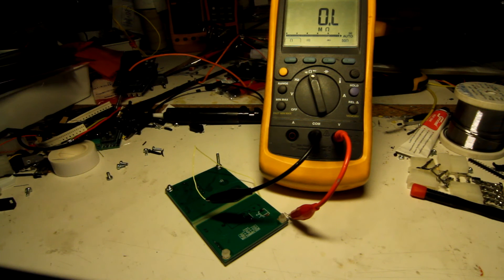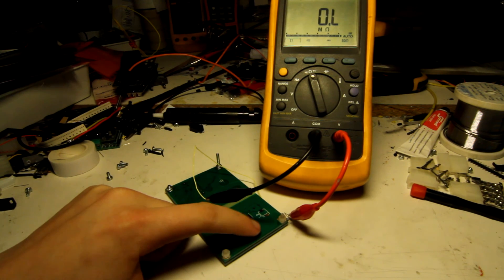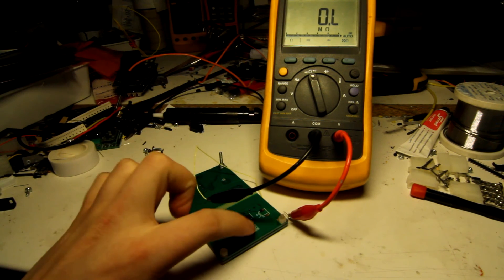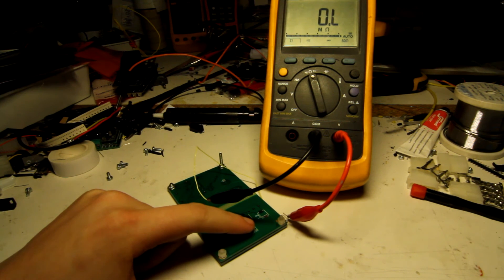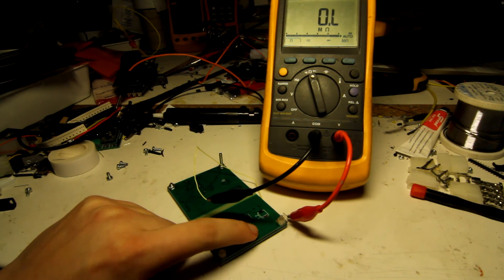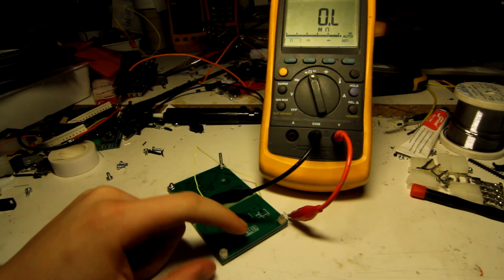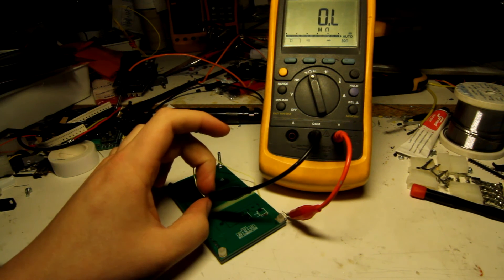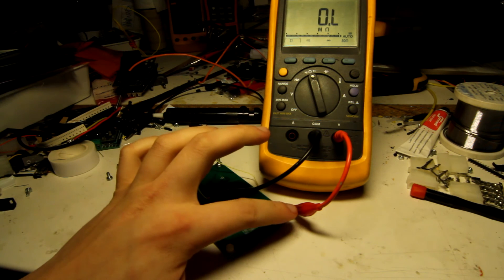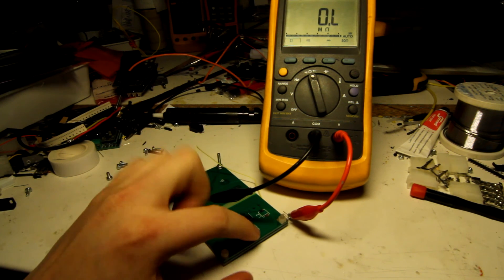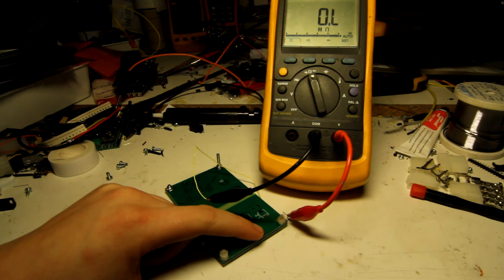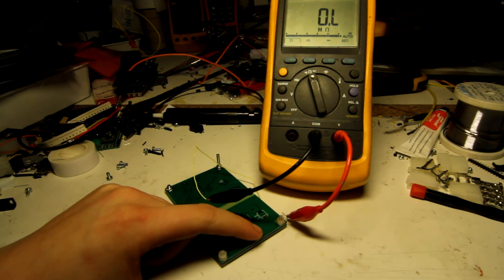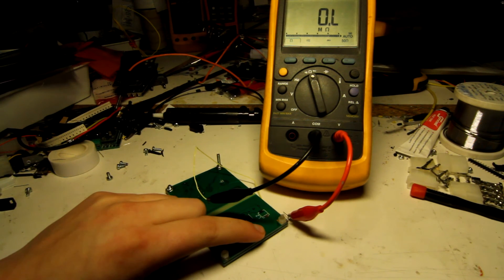So just to show you how strong this effect is, I've got here - it's very hard to get this on camera - I have two PCBs here, and I put a little bit of QTC material in between these PCBs. One PCB is connected to this wire, one to the other, and I'm measuring the resistance. And as I push down, like right now, it's an overload on the resistance scale. So it's essentially infinite resistance.